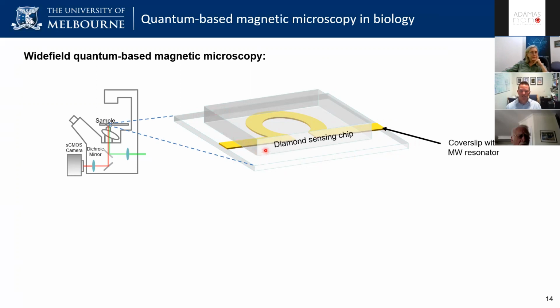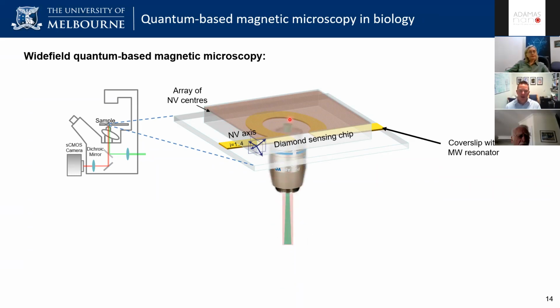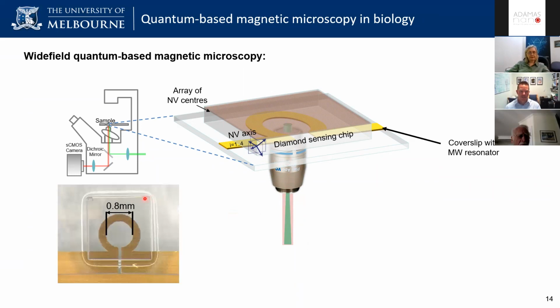single crystal diamond. So these are typically 50 to 100 microns thick. These are electronic grade material. And then into that, we implant a near surface layer of NV centers. So typically our implants would be 4 kilovolts, for example, which would put the NVs about 10 to 15 nanometers from the surface. So now we have this beautiful 2D array of NV centers across the surface of this chip. And then in terms of the imaging, we'll image a particular field of view in this wide field arrangement, and then we'll image that fluorescence onto a CCD camera. And so this is typically what our samples look like.